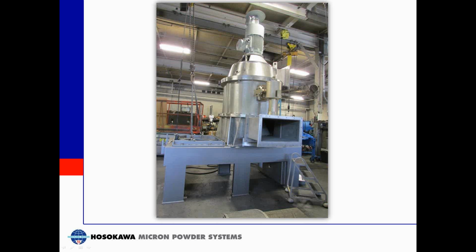Okay. Can you elaborate on the jet mill's size reduction? And I'll talk specifically for the recovered carbon black or the pyrolysis carbon black. What the goal would be is to take, we'll call it crumbs, the crumb size, which could be several hundred microns to say 3 or 4 millimeters, and mill it down to a median particle size, a D50, in a range of 5 to 7 microns, and a top size, so a D97, D99, in a range of 13 to 18 microns.